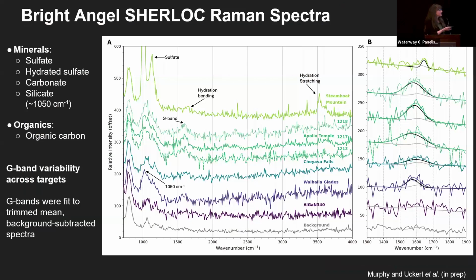If we take a look at the average of that spectrum here, this waterfall plot shows all of the targets. And one of the things that stands out, it's at the top, it's Steamboat Mountain. We have a very strong sulfate signal and it's hydrated. There's a hydrated stretching mode over here in this higher wave number region. So this is consistent with the bassanite mineral. But we don't see hydration in any of the other samples. But we do see this really broad mineral feature, which is consistent with silicate. And in the Apollo Temple, we were able to pull out some sulfate and carbonate signals within there that I'll show in the next slides.